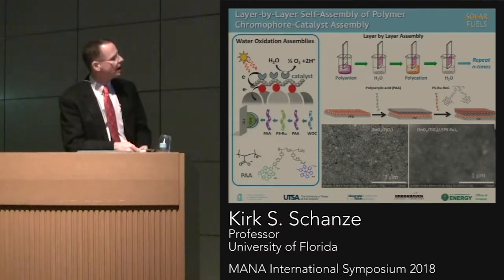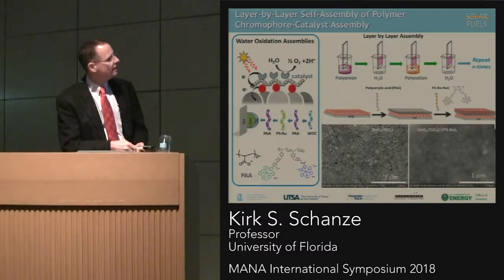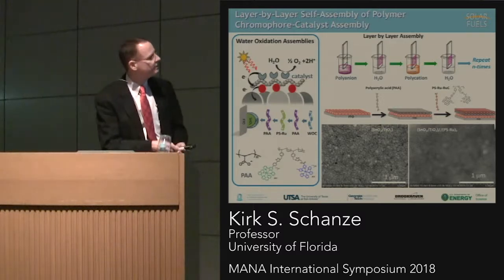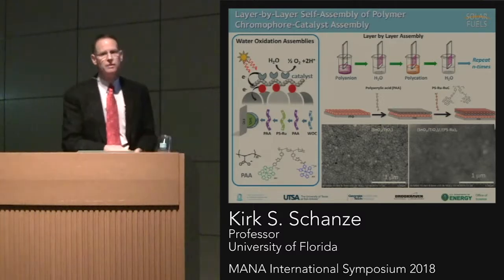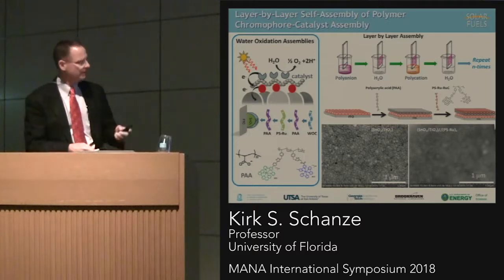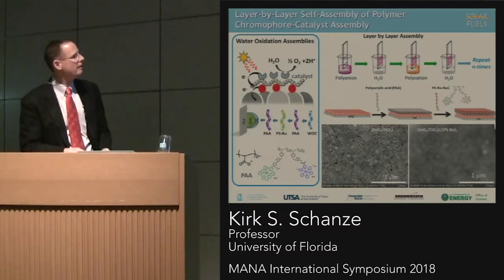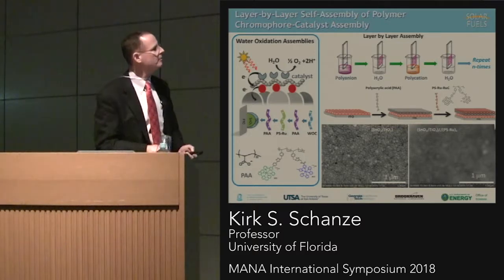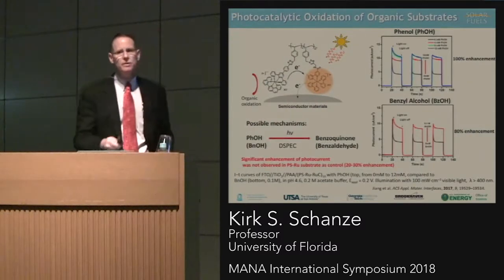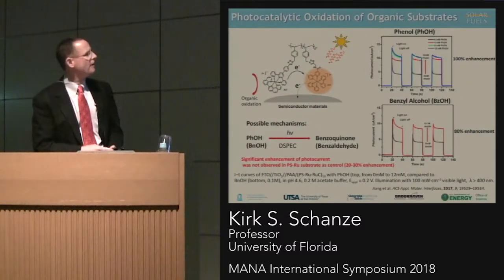And this is a top-down electron microscope image of a metal oxide surface that's then been coated with one of these multi-layer films. And you can see the very distinct change in morphology that signals the coating of the surface by these multi-layer chromophore-catalyst assemblies. So using these now surface-modified electrodes, we then turn again to photoelectrochemistry.